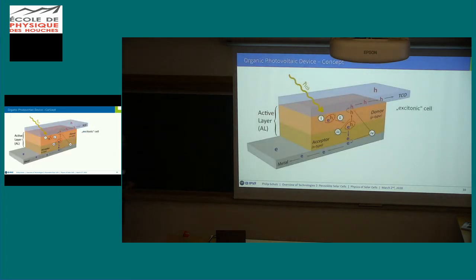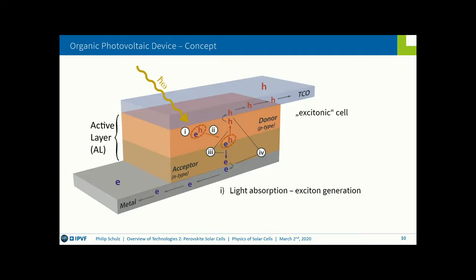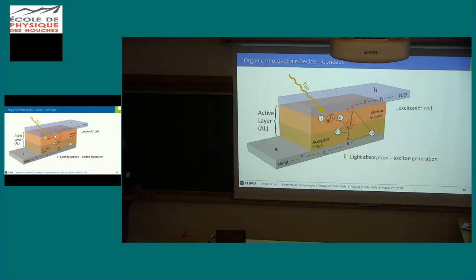Now this is how an organic solar cell works in general. We call it an excitonic cell for reasons that will become apparent in a second. So first we have light absorption that generates an exciton. These are not free carriers, a free electron and a free hole, but this is actually a tightly bound so-called Frenkel exciton with a binding energy that is higher than your average kT, on the order of hundreds of milli-electron volts.